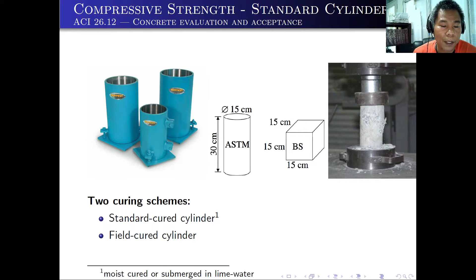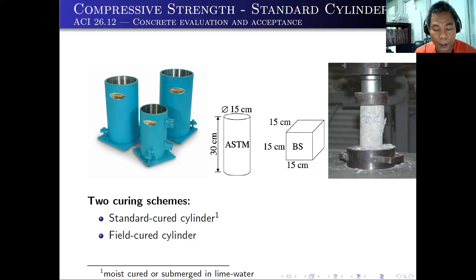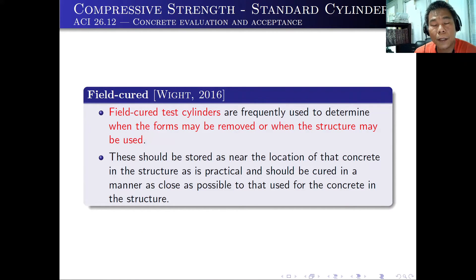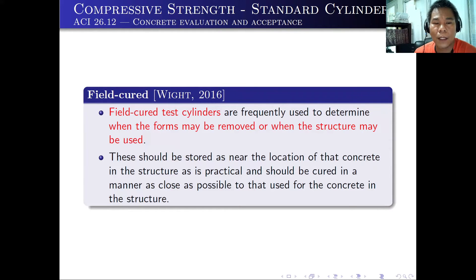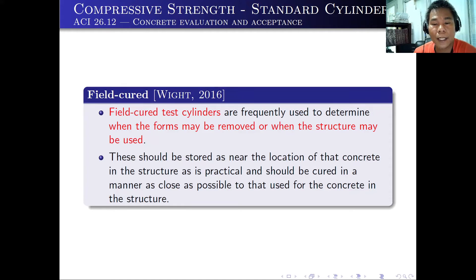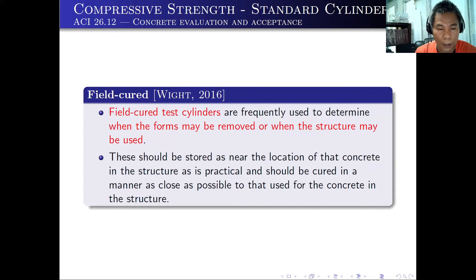There are two curing schemes. You can use the standard cured cylinder that is moist cured or submerged in lime water. You can also have field-cured cylinders. For the field-cured cylinder, the test cylinders are frequently used to determine when the forms may be removed or when the structure may be used. This should be stored as near the location of that concrete in the structure as is practical, and should be cured in a manner as close as possible to that used for the concrete in the structure.